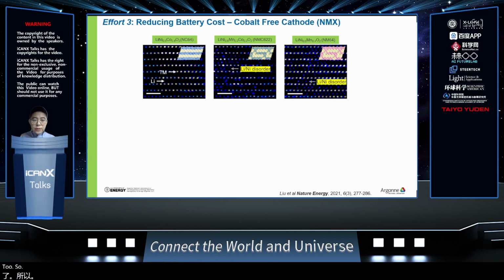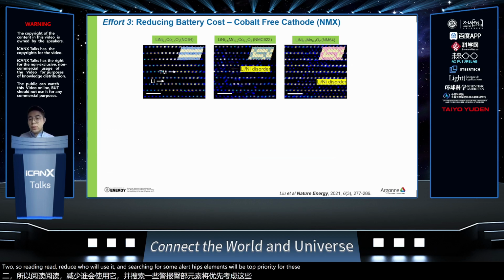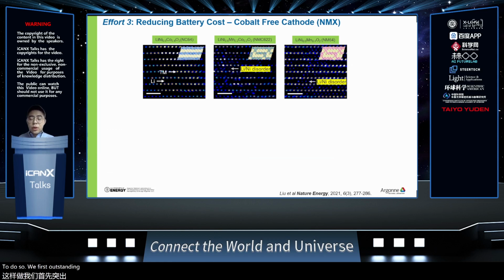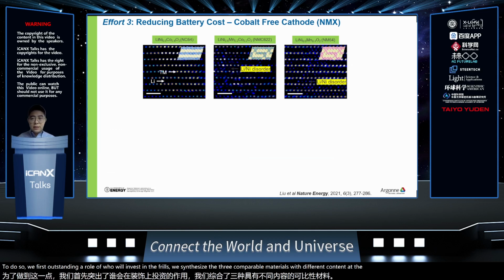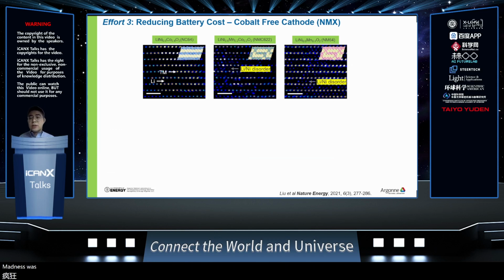So really reducing cobalt usage and searching for alternative elements will be the top priority for these cathode materials. To do so, we first need to understand the role of cobalt in these materials. We synthesized 3 comparable materials with different cobalt content and manganese content. Manganese was selected because its price is only 1% of cobalt.